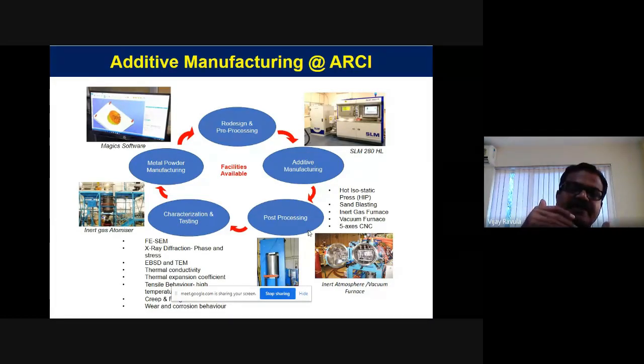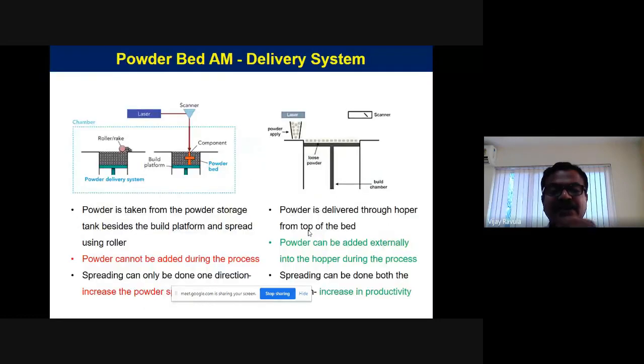But then it also has repeated heating and cooling cycles going on, because you are building the whole component layer by layer. And you definitely need to do the post-processing. So you need furnaces, and if you want to improve the density, you need to have hot isostatic pressing. Then you will also have characterization. So all these facilities are available at ARCI. We have been working on and developing many components, many of those things.